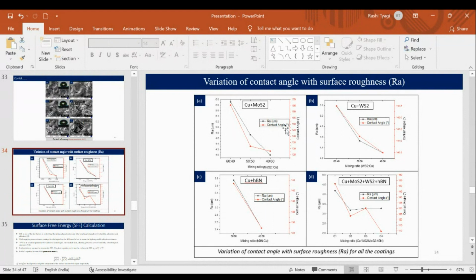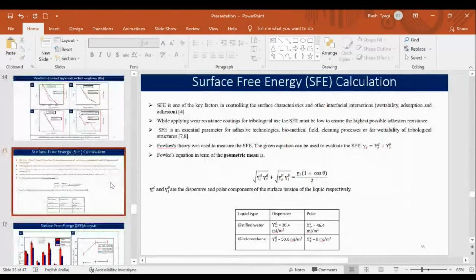So we have observed that a high surface roughness is observed at 6 micrometer. We have obtained a maximum 165 degree contact angle for copper plus MoS2 coating. So at maximum surface roughness, maximum contact angle is observed according to the Wenzel model. So we can say that by increasing the surface roughness, we can obtain the superhydrophobic coating.